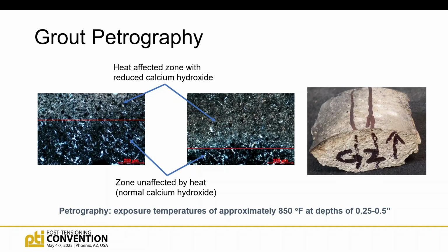I mentioned the grout's a little different because we don't have the aggregates to give us that color telltale. So once again, now we're looking at changes in the amount of calcium hydroxide they can see. Calcium hydroxide is the main residual component left of cement hydration, and it gets cooked off during a fire. And so they were looking at lines, differences in calcium hydroxide, as you can see by the red lines there, to determine the effective depth of heat on those two grout samples. And you can see we cut several of them up into quite small segments so they could do a detailed petrography on that one.